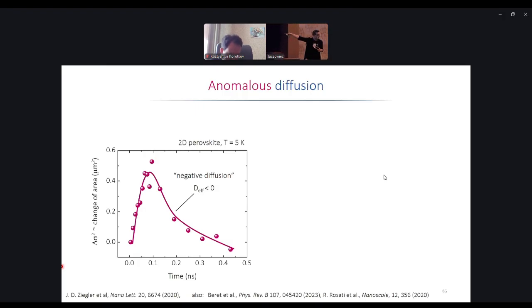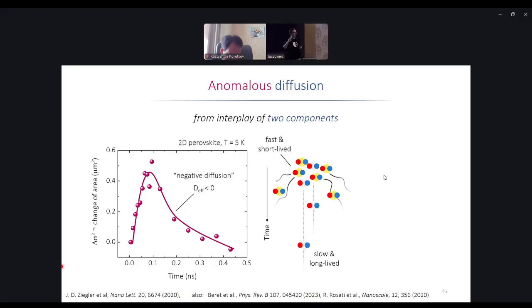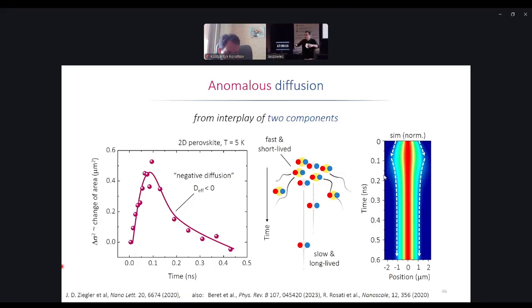But this is observed, and usually when you have something like this, you can again imagine excitons now not repelling each other, but attracting each other. This definitely can be a model explaining this type of observation. But even simpler, imagine the following, you have two components. Again, think about localization. You have a component that expands very fast and is short-lived, and you have a component that doesn't move but is long-lived. If you have a situation like this, a two-component diffusion, that will quite often lead to such very unusual anomalous diffusion phenomena. So you have an apparent expansion and a contraction of the exciton cloud.